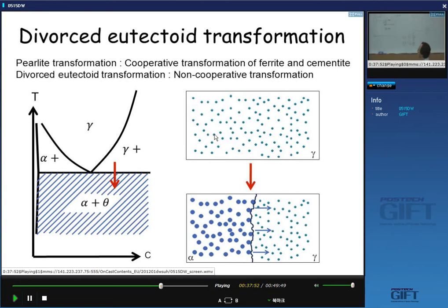And how can we make this kind of seed? Just hold the sample in two-phase region of the austenite and cementite. And some part of the lamellar cementite dissolved and fragmented and have this round shape, very small seed. Then we cool down the sample with very slow cooling rate. I told you very slow cooling rate, which permit